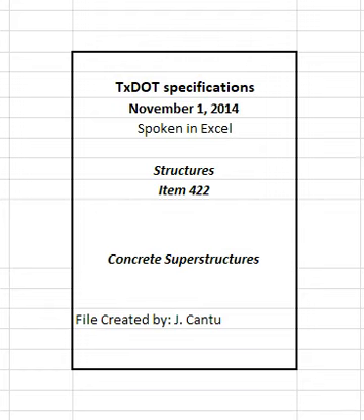3.7 Sawing equipment. Use sawing equipment capable of cutting grooves in completed bridge slabs and top slabs of direct traffic culverts. Provide grooves that are 1/8 to 3/16 inches deep, nominally 1/8 inches wide, and spaced at 1 inches. Use sawing equipment capable of cutting grooves in hardened concrete within 18 inches of the barrier rail or curb.